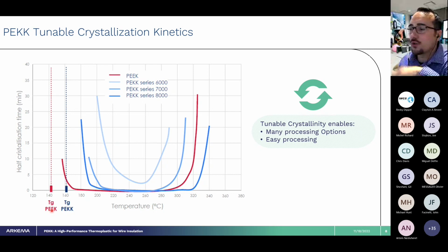We've also called out the TG of the PEEK material and the TG of our PEKK—the red line is PEEK. At 180 degrees C or so, you're more or less going to be crystalline immediately.